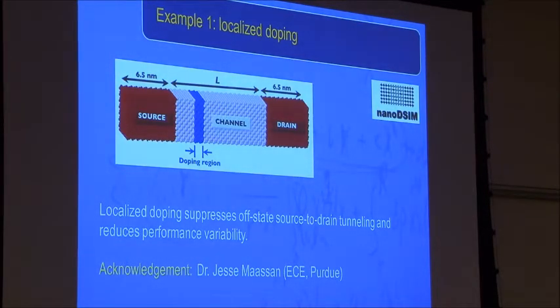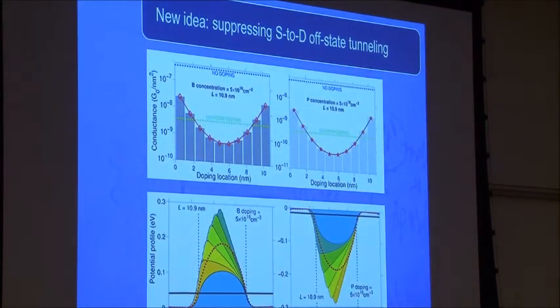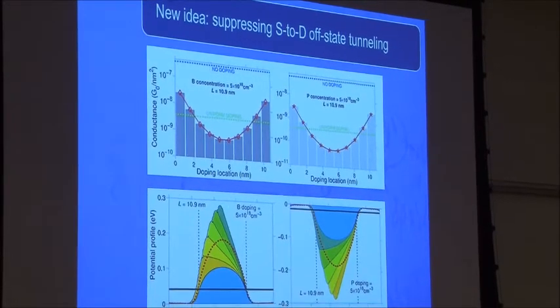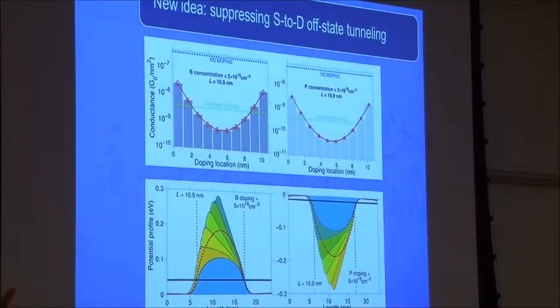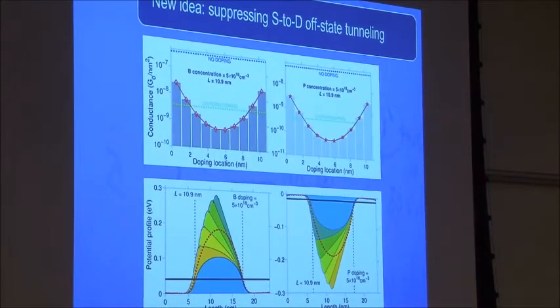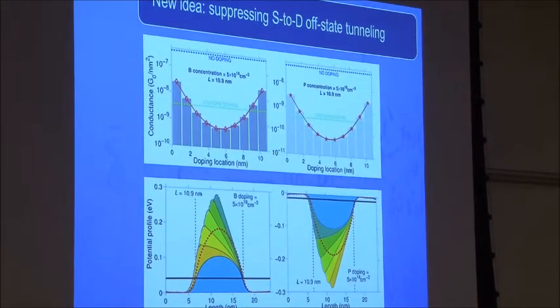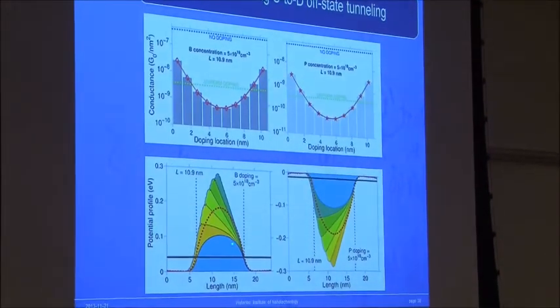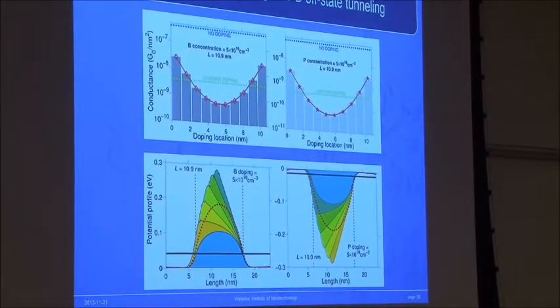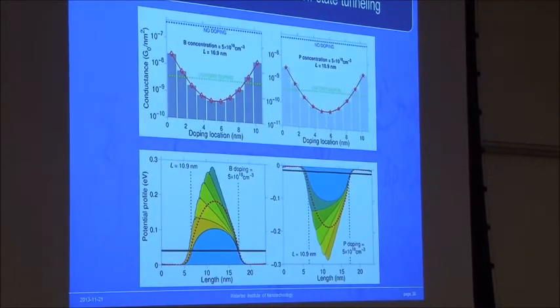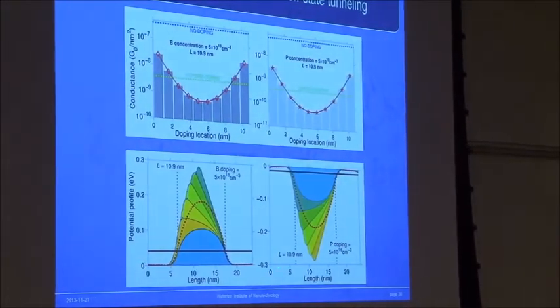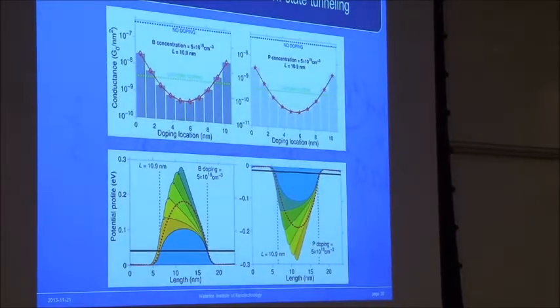So basically we took this and did the calculation with the right doping, with the right gaps and so on. And indeed, that's exactly what he found. What he found is that if you dope in the middle, your potential is much higher. But this doping potential is actually a long-range electrostatic potential. So even though you only dope this region, the potential leaks out. So you actually still have a wide width, but you have a much higher potential. If you uniformly dope, you get this lower potential, so you have larger tunneling. Okay, so you can easily tunnel through there, and this one has more difficulty to tunnel through. Whether you N dope or P dope, it's the same kind of physics.